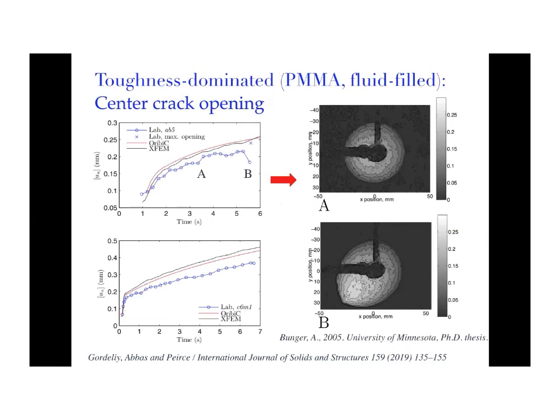Okay, so this fracture is not just elliptic. I mean, it completely lost its symmetry, right? And also in experiments, they actually noticed that there is also mode 3. So there was something not just captured right now in the model. I think for all of this, we would need to develop actually a 3-dimensional model. Which means right now the model is essentially 2D and the crack is essentially a line or a curved combination of segments of lines.